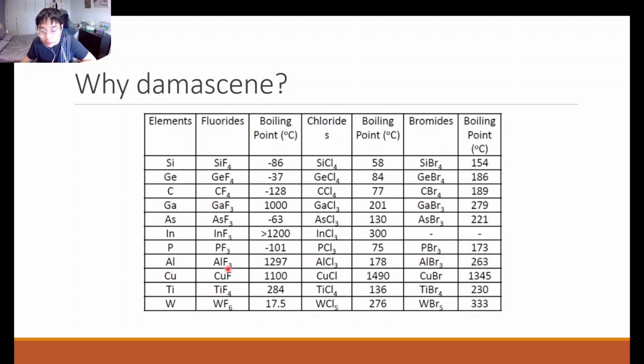However, if you use copper as your metal, copper fluoride, chloride and bromide all have very high boiling points, and so they are not volatile gases. That means that even if you use a halide based etching gas, the resultant etching byproducts are not volatile and cannot be readily removed from the wafer. That is why copper cannot be easily etched away, because the byproducts will still stay on the wafer, very difficult to remove and cause contamination. So copper cannot be cleanly etched by a dry etching mechanism.